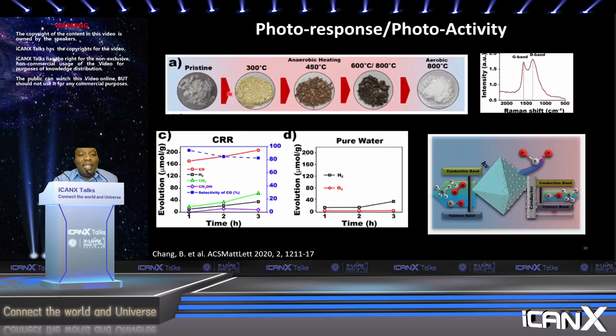And as you start heating it up, you see it turning yellow, turning brown, turning dark brown. And then you heat it in there, it goes all the way back to white. We confirm that this is graphitic carbon, but we have a mixture of graphene and graphene oxide using Raman spectroscopy.